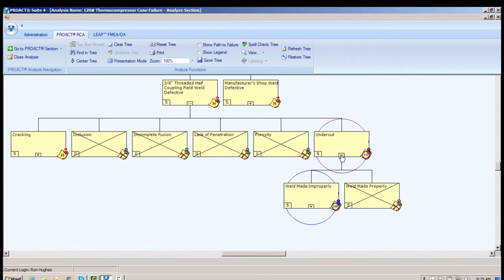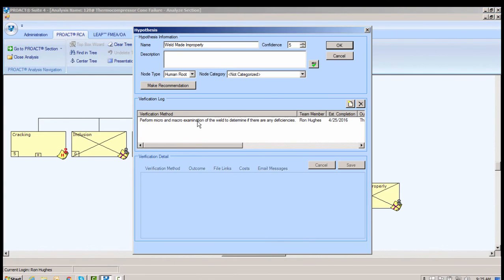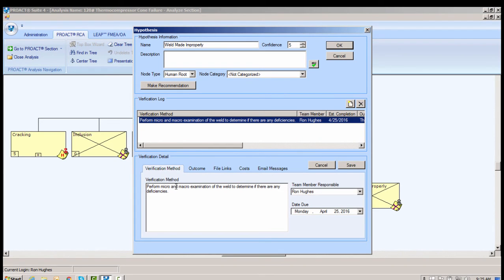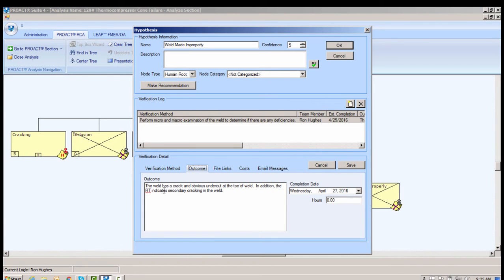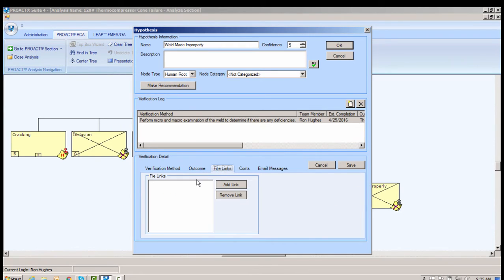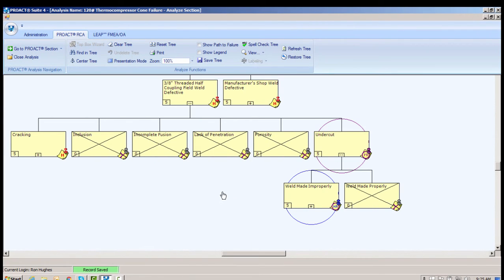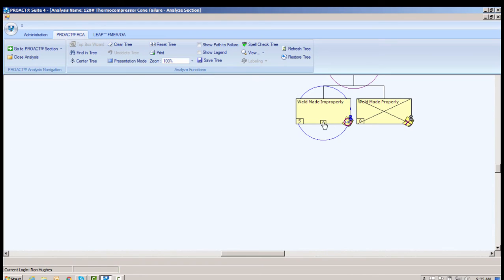So how can we have undercut? Well, either the weld's made properly and we have undercut, or the weld's not made properly. And obviously the weld is not made properly, or we wouldn't have undercut. Also, we do micro and macro examinations, and we can see the defects in the weld. And the defects is the weld has a crack, an obvious undercut at the toe of the weld. In addition, the RT indicates secondary cracking in the weld. Okay? That means the weld is made improperly.